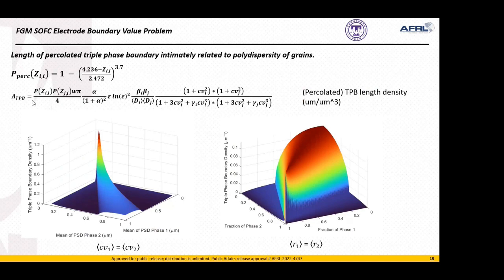Now, the triple phase boundary is also dependent not just on the standard deviation, but also on the mean. You can see the critical nature here of this percolation threshold. So looking at the triple phase boundary density map on the left-hand side, there are areas where if the mean of phase one and phase two, this could be nickel, YSZ, or you could think about particles on the cathode as well, where if those means are too disparate, then you're not going to get an effective percolating triple phase boundary.